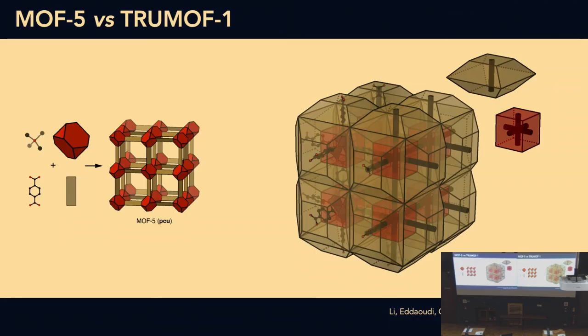So here, this is the kind of canonical metal-organic framework. It's something called MOF-5. And let me quickly summarize its chemistry. The metal bit is this tetrahedral cluster of zinc atoms. And those clusters have chemical connectivity that means that they will bind 6 carboxylates in an octahedral arrangement. So we link them together by taking a dicarboxylic acid, in this case 1,4-benzene dicarboxylate, and that's this panel here. So it can fit 6 of these around each of these clusters in an octahedral arrangement, and each one of these will connect 2 clusters. So when you do that together chemically, you produce this very simple cubic arrangement of clusters and linkers. So that's the ordered arrangement.